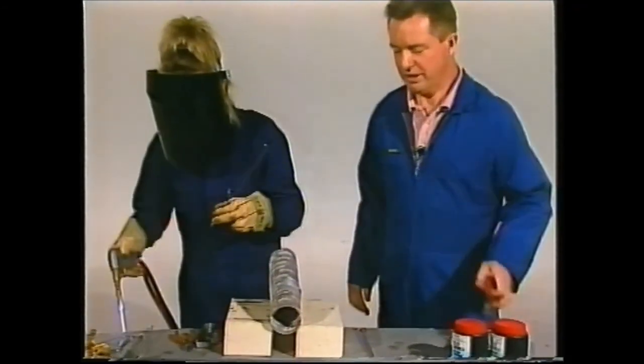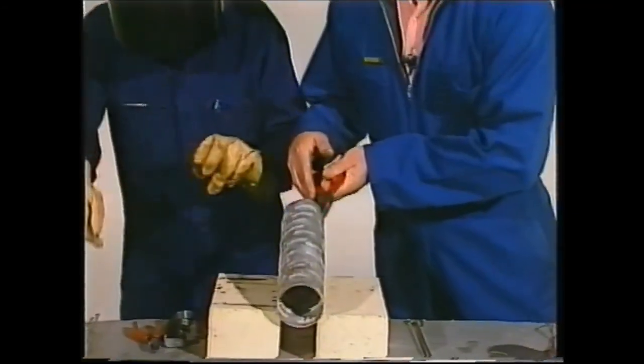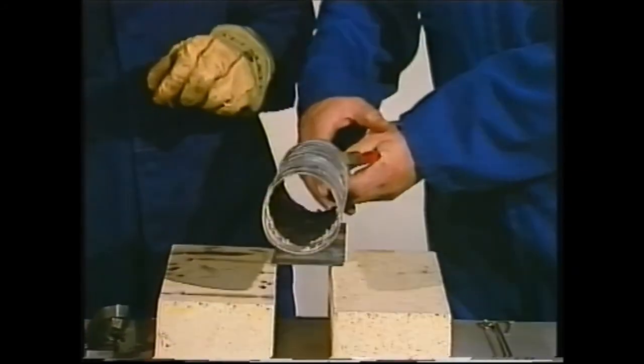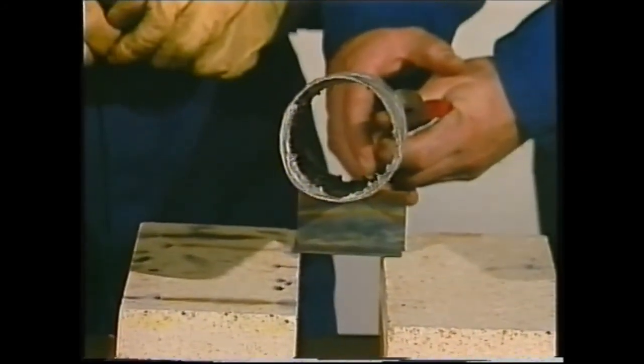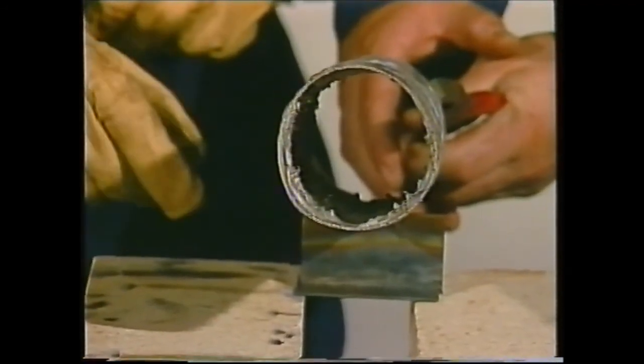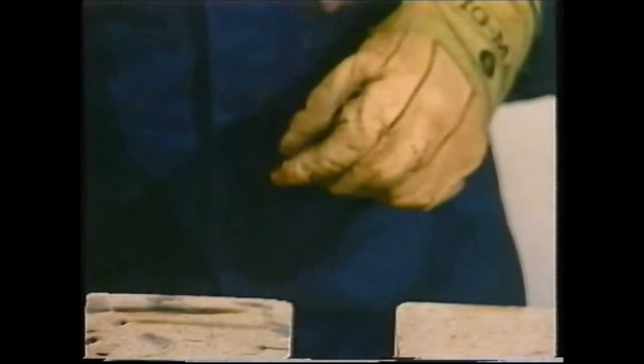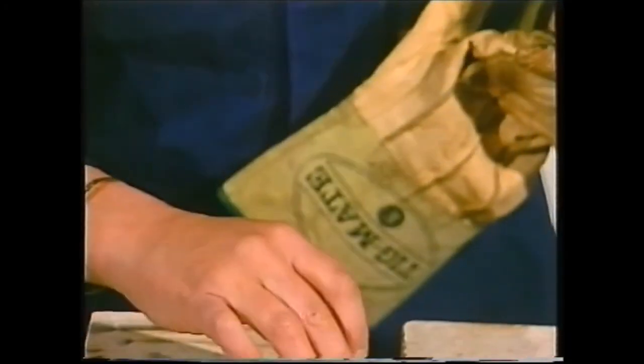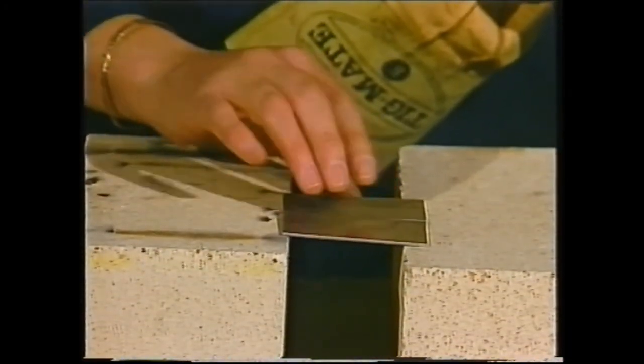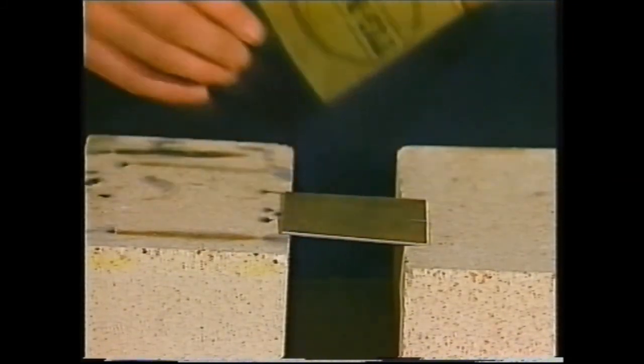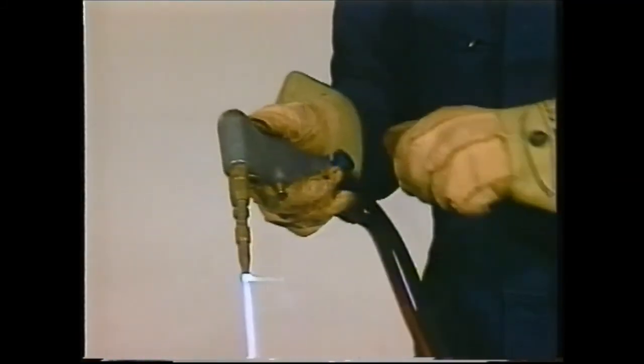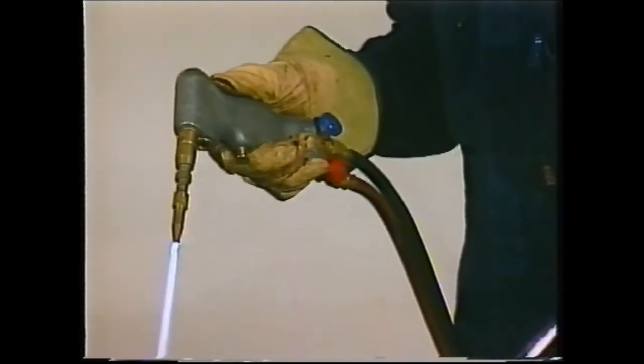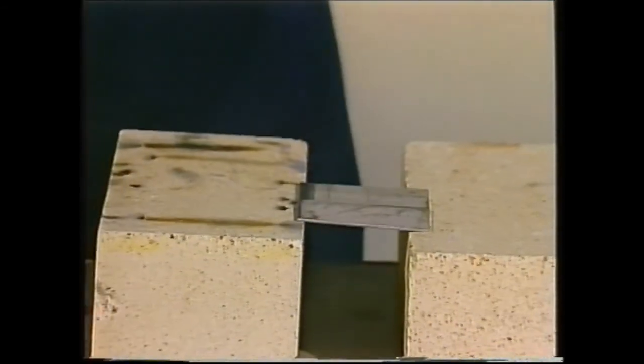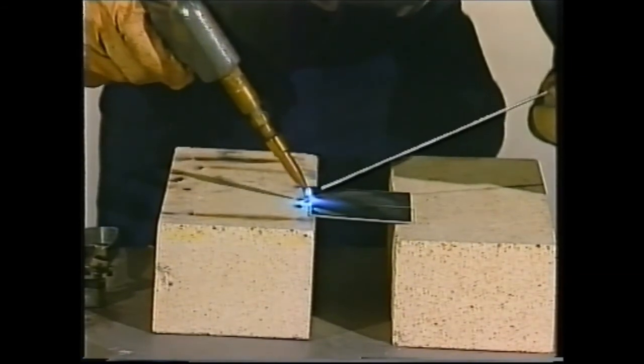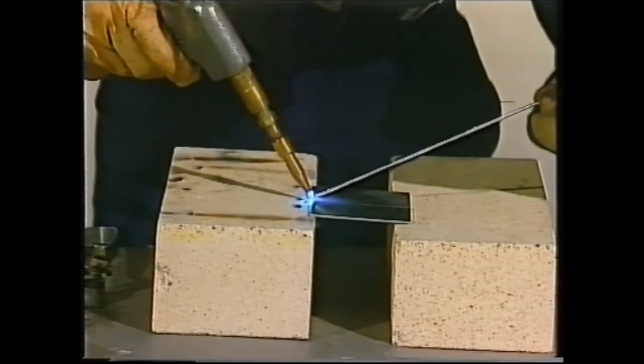You can see there quite clearly how beautifully that repair is done, and if I hold this slightly up, you should be able to look inside the pipe and see the penetration of those welds. Now, we'll drop this in our water, and we'll now demonstrate using some 1.6 mm aluminium, just to show you again the torch's remarkable abilities with thin aluminium. Again, just using standard filler rod. Notice here we have a slight bit of flux on the rod. It's just standard SIG flux that we mix with a little bit of water and put on the rod, just to break into the oxide layer for aluminium.